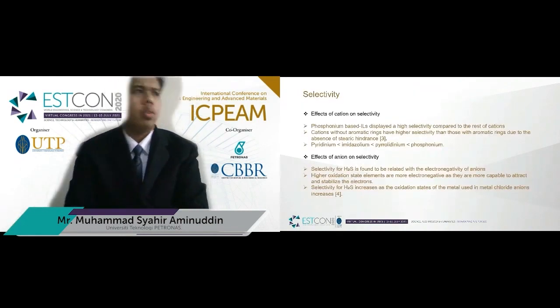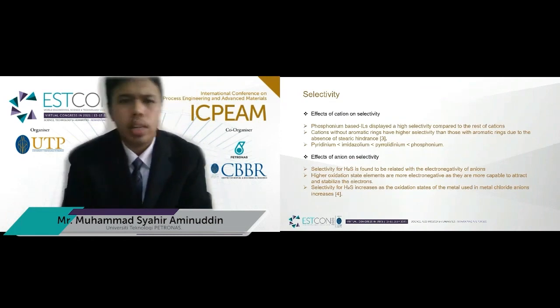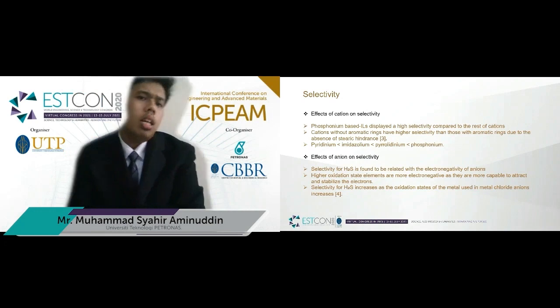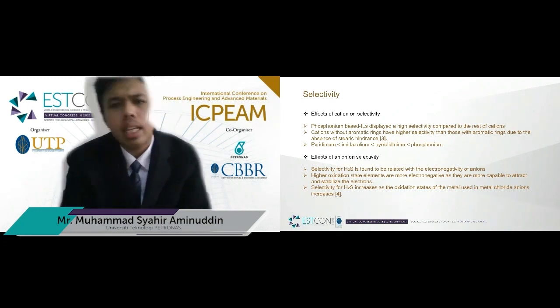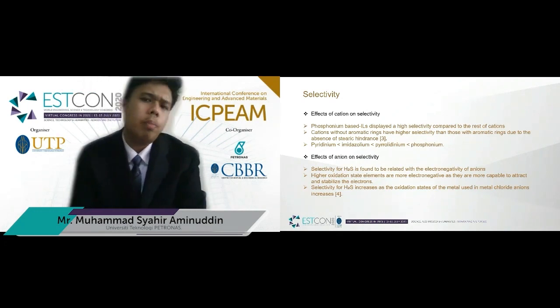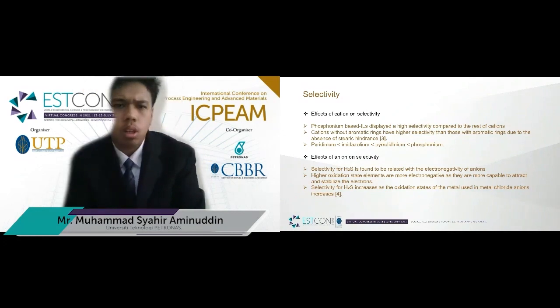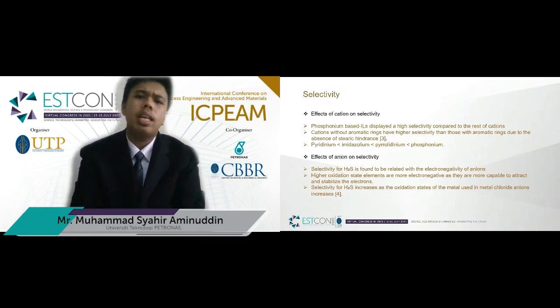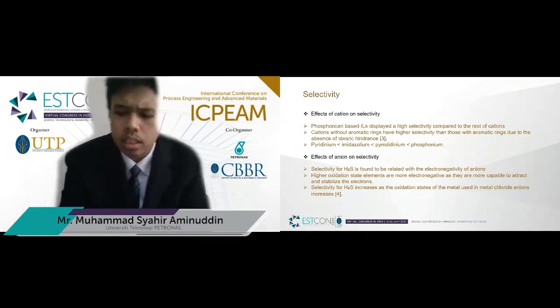Then we will proceed with the selectivity. Selectivity is affected by the cations and anions of the metal chloride anion-based ILs. For the cations, the phosphonium-based ILs display a very high selectivity compared to the rest of the cations. This is because cations without aromatic rings have higher selectivity than those with aromatic rings due to the absence of steric hindrance.